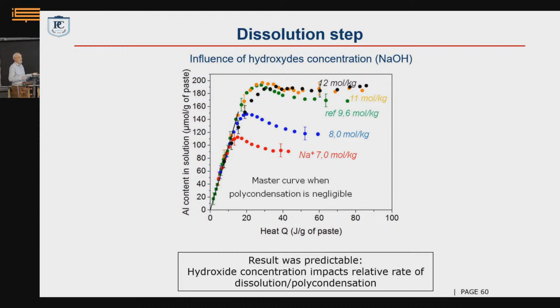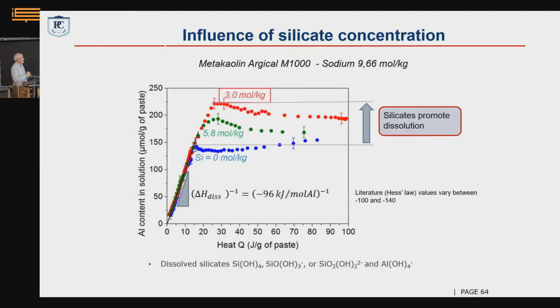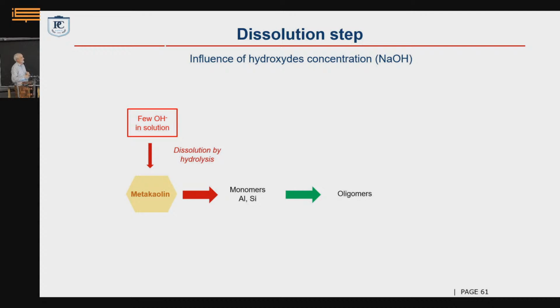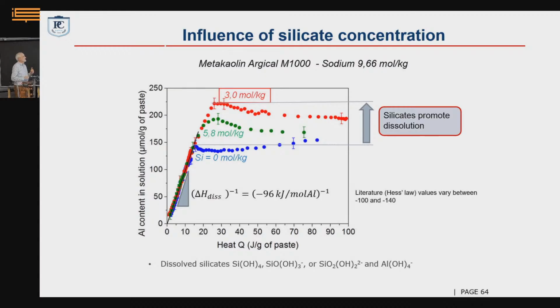Okay, we recover something that was very expected, that the hydroxide concentration actually changes the completion of the reaction. So it changes the moment where we switch from pure dissolution to dissolution plus polycondensation, but the initial dissolution mechanism is always the same. So the beginning is very clear. We have hydroxide in solution. They attack the clay. They release the monomers in solution. Okay. Where it gets more interesting is to understand the role of the silicates.